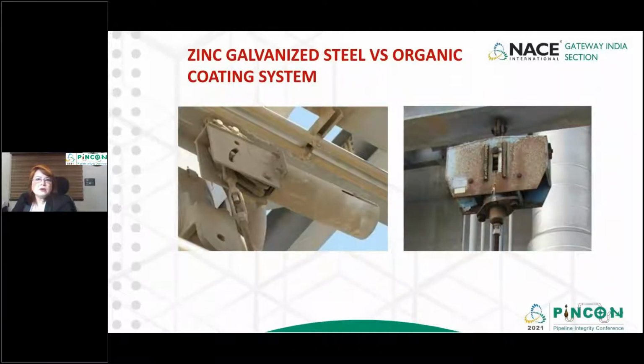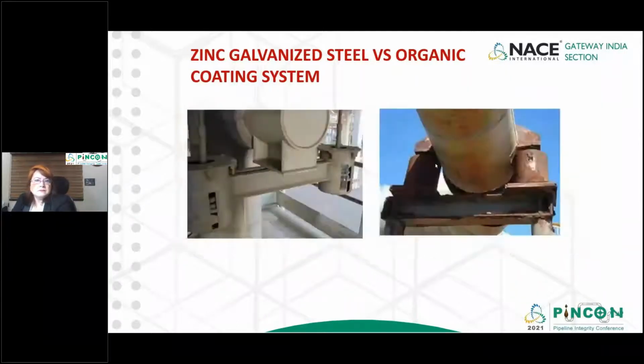Zinc galvanized steel versus organic coating system. With zinc, we see there is no corrosion, again against the organic coating versus a galvanic system. This is a simple organic coating, where corrosion starts.